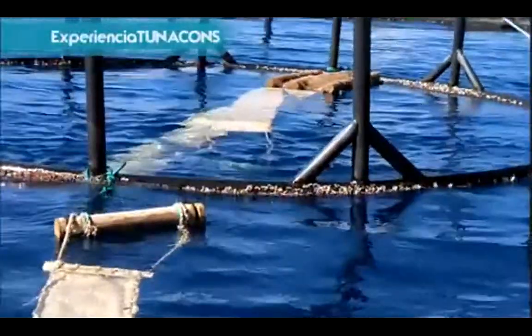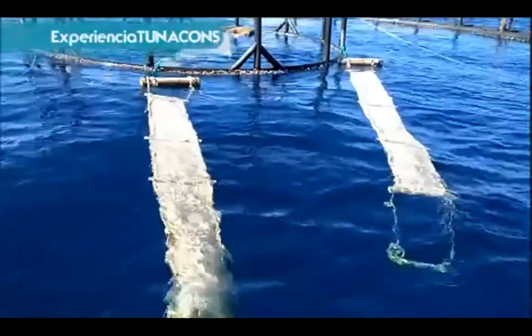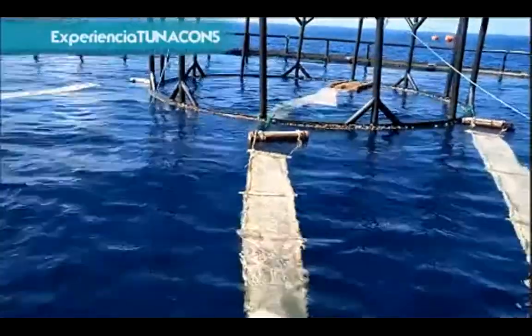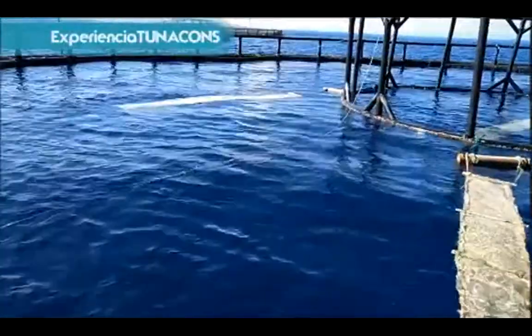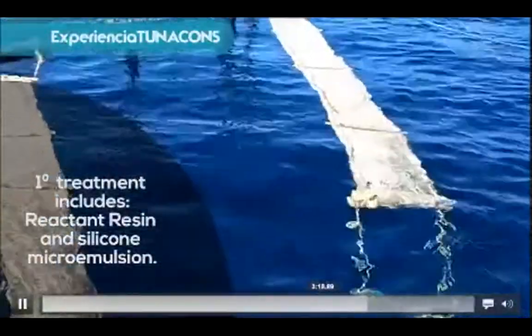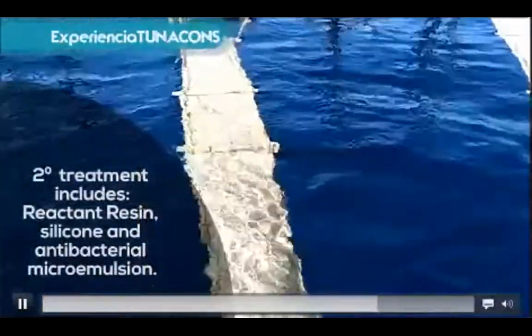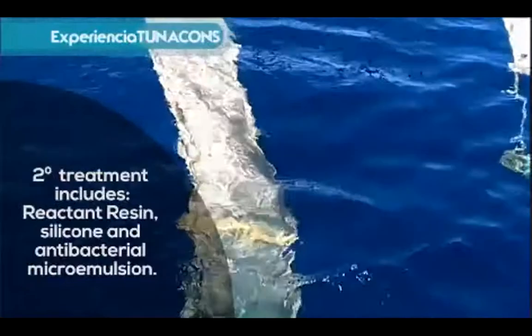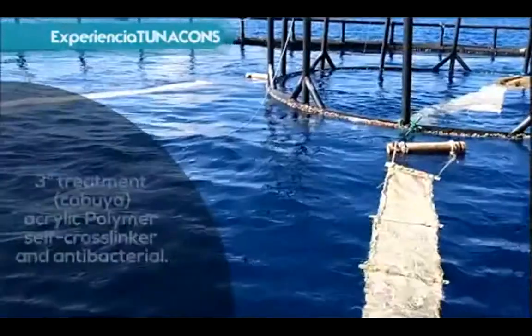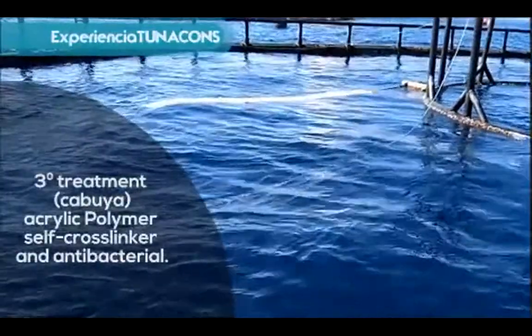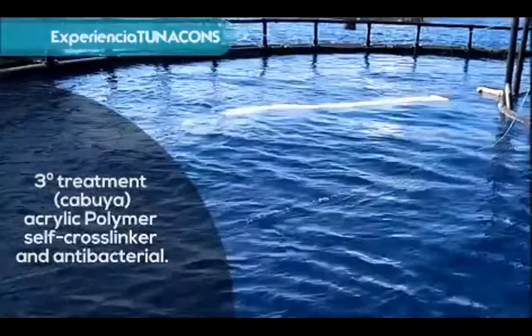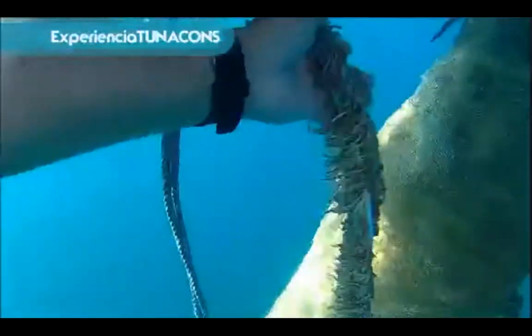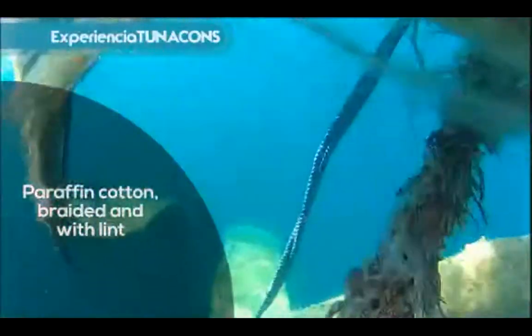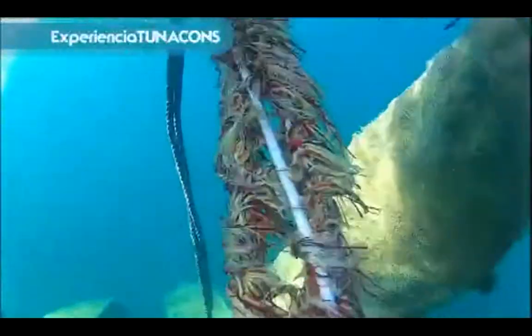2 different treatments were applied on the abaca fiber and also to the cabuya fiber so that they could be tested at the same time. The first treatment includes reactant resin and silicone microemulsion. The second treatment includes reactant resin, silicone, and antibacterial microemulsion. The third treatment was only for the tissue of cabuya and has acrylic polymer self-cross-linker and antibacterial. In this deployment of samples, we also test the resistance of paraffin cotton, braided and with lint. The images that are shown here are of the fabrics with treatment after 31 days at sea.